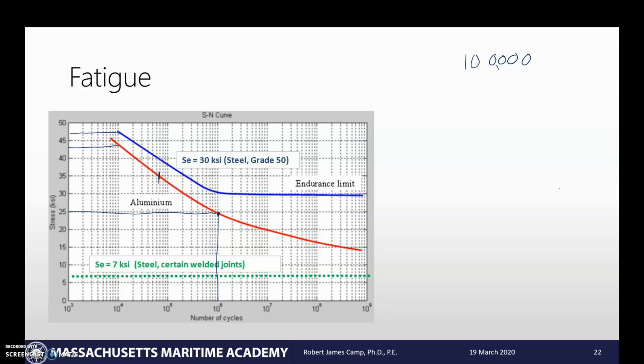I've done this in my own career. I was investigating why something was breaking because they took a mirror that they had in a scanner, like at the grocery store, and they couldn't understand why the new one was breaking because they'd had the old one for years and it never had a problem. Well, what the engineers had done is they just scaled it up by twice, and they never even thought of looking at the fatigue limits. After about 100 hours of operation, it was passing the fatigue limit because they made it twice as big, put a lot more stress on it, and the things were disintegrating. It's kind of funny, but we figured it out.